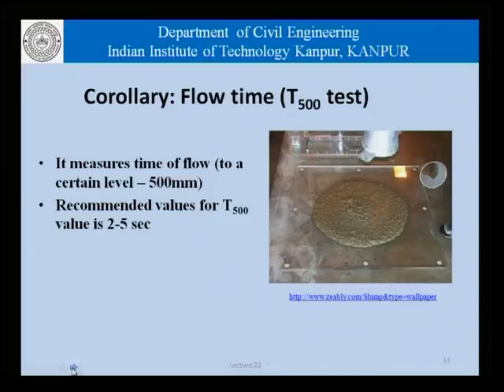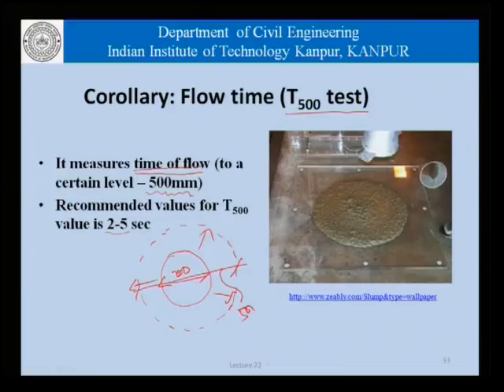As a corollary to the slump flow test, we also sometimes use a flow time, which is sometimes called the T500 test. And now, this T500 refers to the time it takes for a concrete to achieve or reach a diameter of 500 millimeters, and the typical time could be in the range of 2 to 5 seconds. So, as the slump cone measuring 200 millimeters in diameter is lifted, the concrete spreads in all directions, and we look at the time that it takes for the concrete to reach a diameter of 500 millimeters, and this time is called the T500.